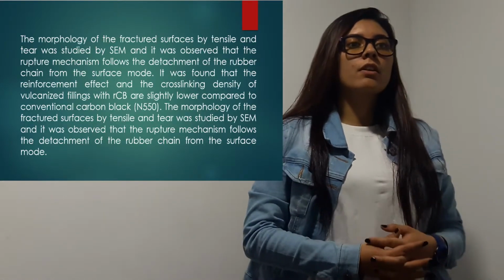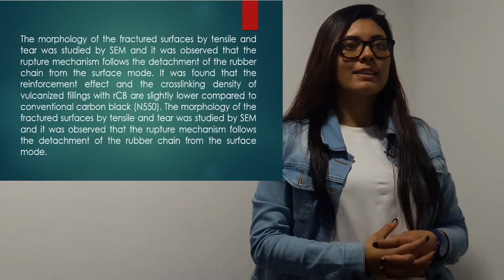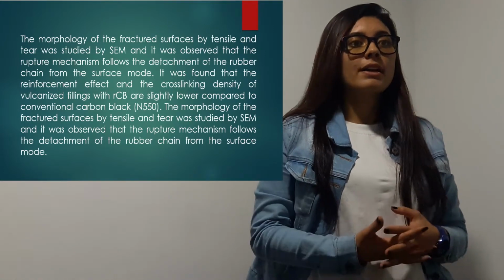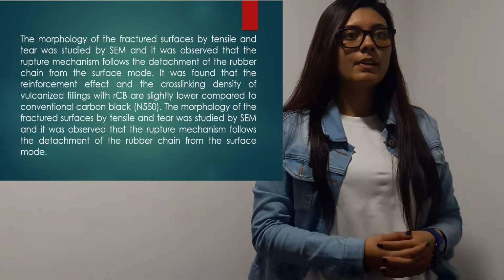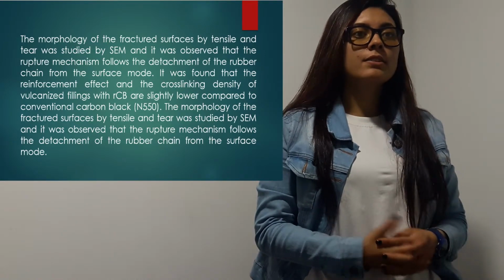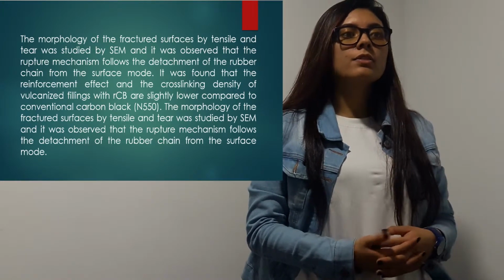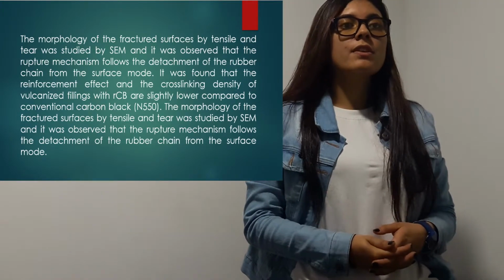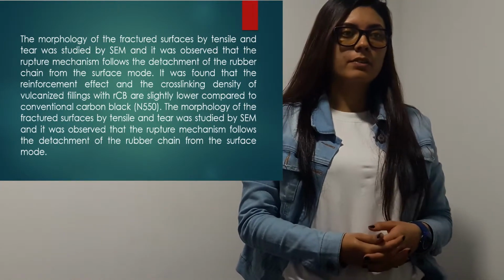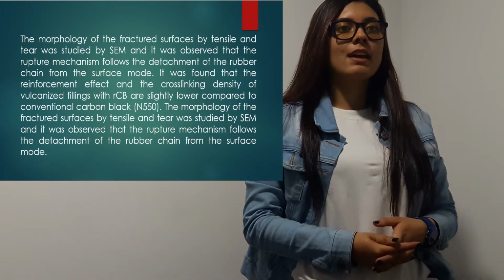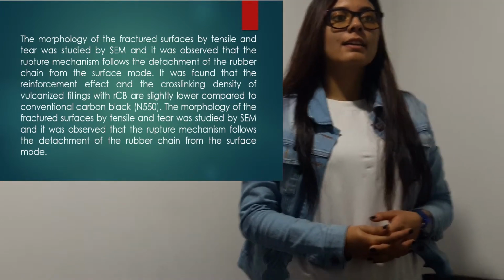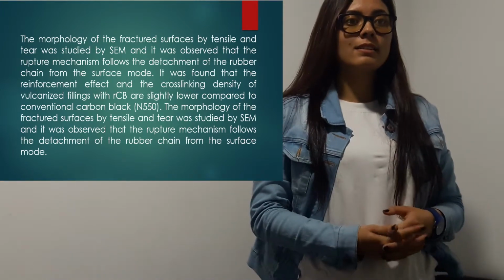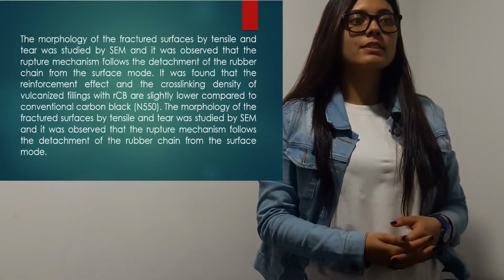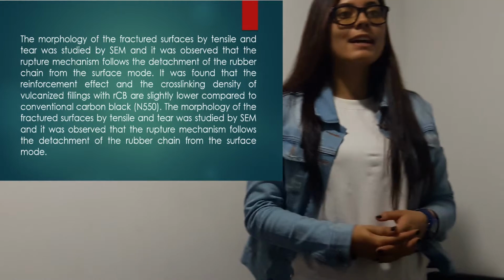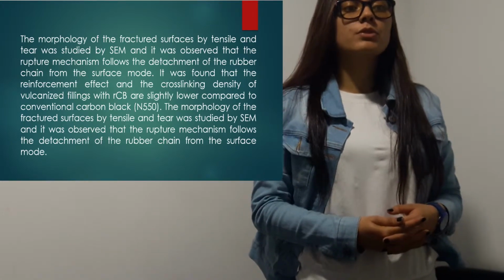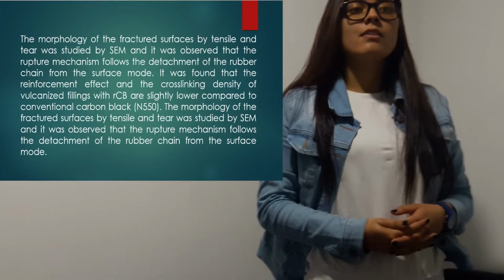The morphology of the fracture surface by tensile test was studied by SEM, and it was observed that the rupture mechanism follows the detachment of the rubber chain from the surface of the filler. It was found the reinforcement effect and the cross-linking density of vulcanized fillings with RCB are slightly lower compared to conventional carbon black N550.